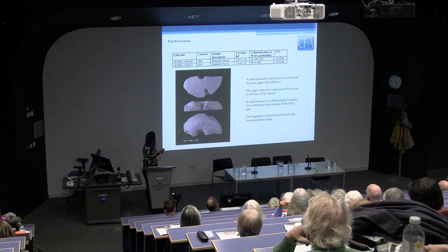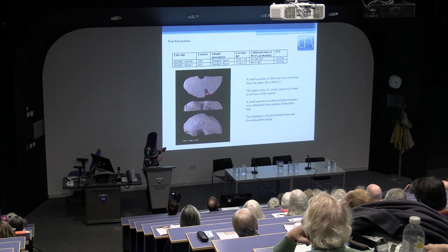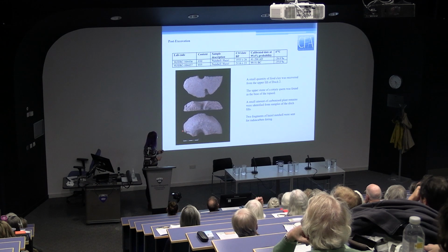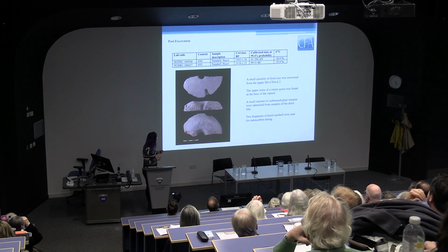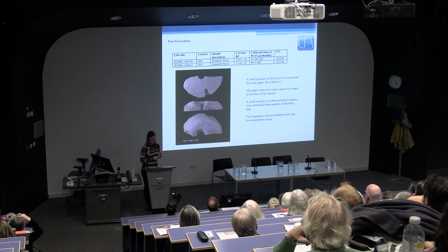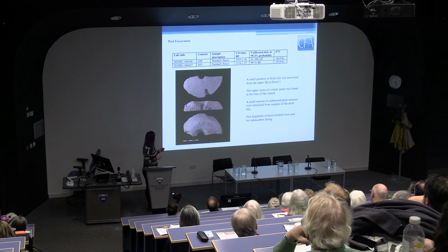We then had this lovely quernstone, the upper stone of a rotary quern. This had 2 handle sockets, one in the side and base, as it turns out here, and then a second one just here in the top edge where it's broken. As you can see, the side handle socket has worn through to the grinding surface, suggesting it was in use for an extensive period of time. And also, the addition of the second socket suggests that people were continuing to use it and repairing it.